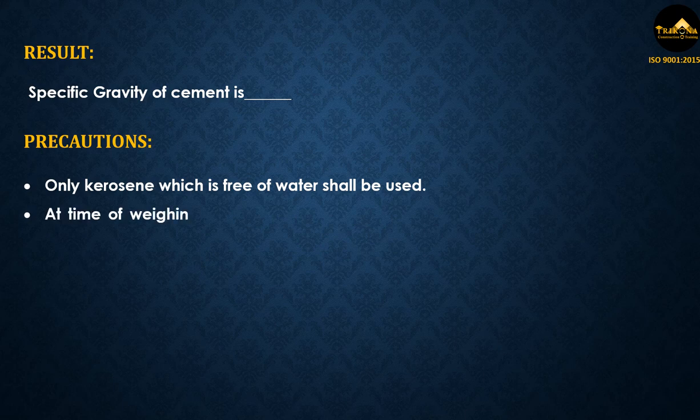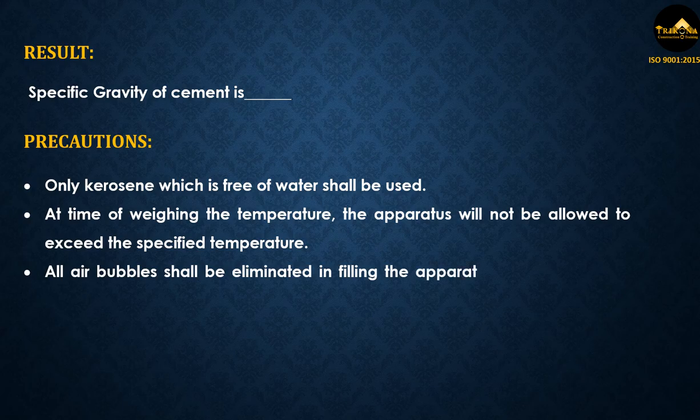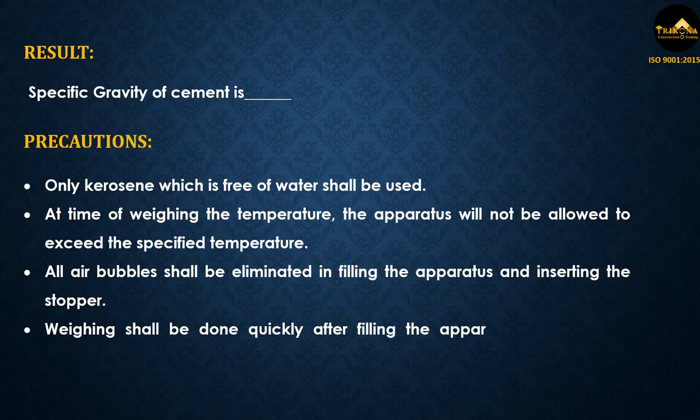At time of weighing, the temperature of the apparatus shall not exceed the specified temperature. All air bubbles shall be eliminated when filling the apparatus and inserting the stopper. Weighing shall be done quickly after filling the apparatus and shall be accurate to 0.1 mg.